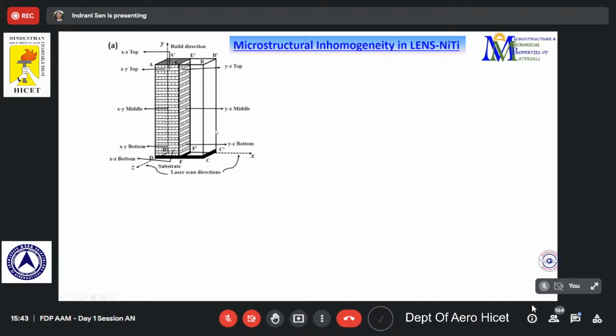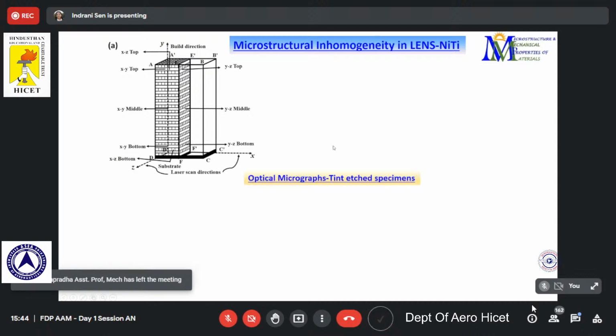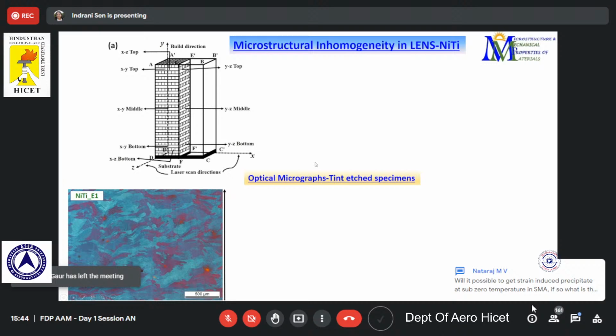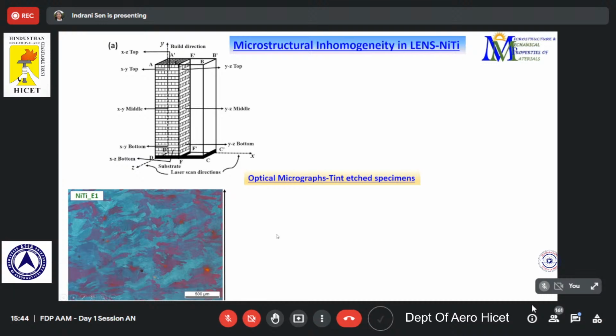Now it is a complicated microstructure that it is supposed to form because of this layer by layer addition. To figure that out, we have done the microstructural analysis at the top, middle, bottom, front, back, at the cross section, everywhere. What we can see in these optical micrographs, with the tint etch that gives the different colors, is that the different layers become very clear. Not much difference could be found here, but this layered structure, this is the EBSD one, shows that this is a layer by layer formation process. So still no clue about the differences in the microstructure.